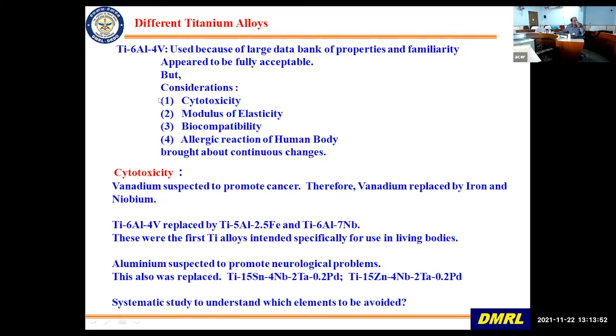It has got cytotoxicity. It has got higher modulus of elasticity as compared to bone. Bone modulus is around 30 to 50 GPa, and this modulus is around 120-130 GPa, so much higher. So there is a problem of load shedding, etc. And then biocompatibility, and then allergic reactions. What is cytotoxicity? This vanadium in Ti6-4 is suspected to promote cancer. Therefore, over a period of time, vanadium was replaced by iron and now niobium.